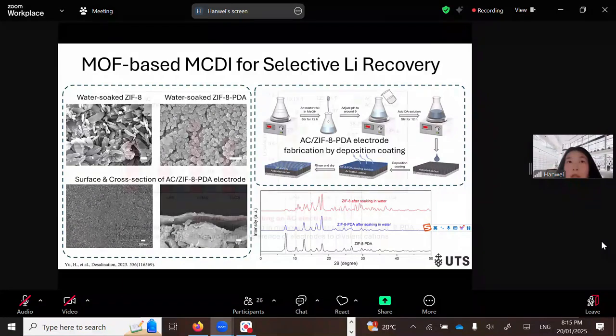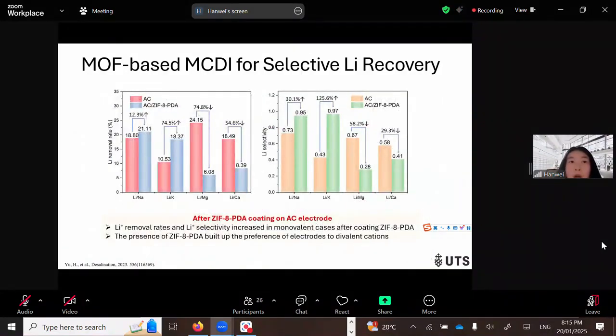So after the ZIF-8 coating, we ran the MCDI experiment under the same condition as the previous test, and the results show that the lithium removal rate and the lithium selectivity increased in monovalent cases after coating, and the presence of the ZIF-8 polydopamine built up the preference of the electrode to divalent cations.